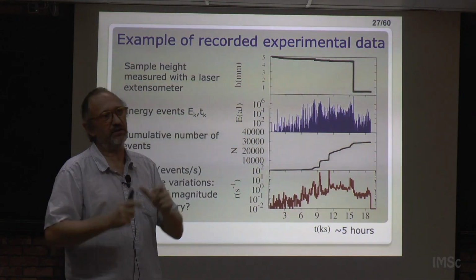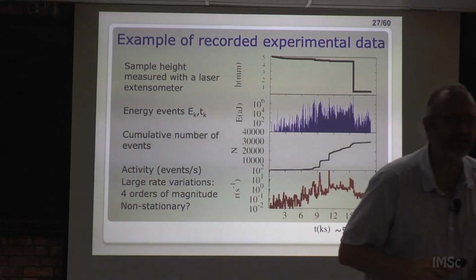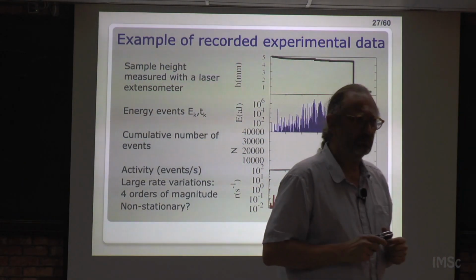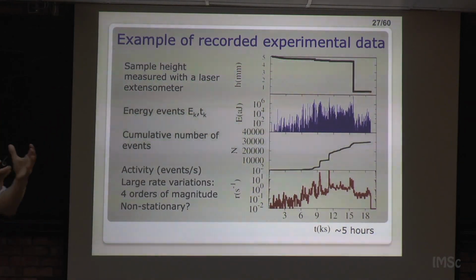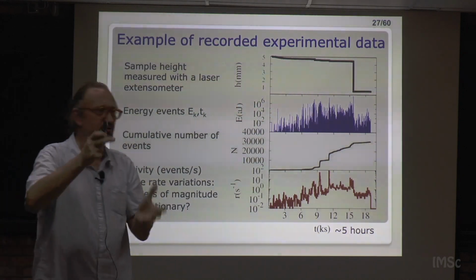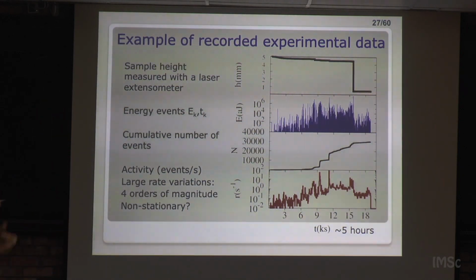But you can get a similar structure just by sintering powder. But it's statistically isotropic. It's rather isotropic, yeah. I mean, you cannot discard that some of the samples have some anisotropy, but it's rather isotropic.